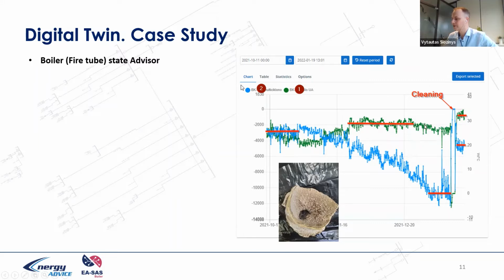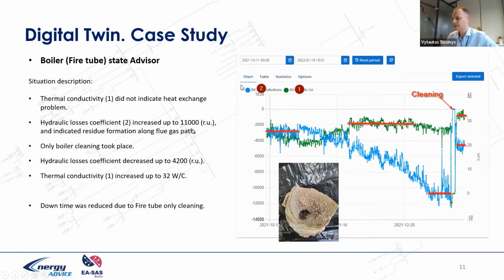And from the thermal conductivity, we see that there was no problem. In fact, it's almost even better, but the hydraulic losses coefficient was increasing, and the decision was made to clean only the fire tube side, so the client saved cleaning time, because the furnace did not have to cool down to temperatures where a human can enter inside. It is only the fire tube side, and after cleaning, the hydraulic losses coefficient returned almost to the level of the good condition of the boiler. A little bit of losses still exist, probably due to furnace condition.